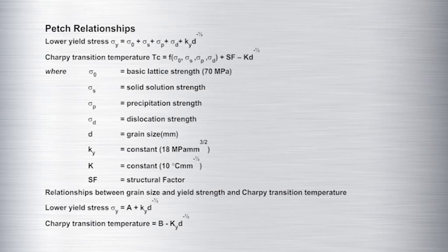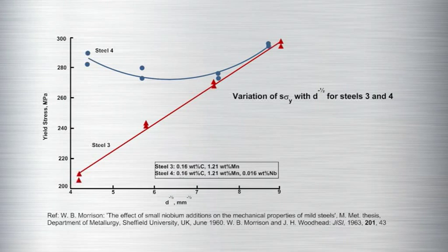It was found that the niobium effect was primarily due to a precipitation hardening effect. By heat treating the steel samples at different temperatures to try to plot linear Petch plots, we found that the niobium-treated steel did not obey the Petch relationship. At coarse grain sizes, there was a very large effect of niobium on the strength, but at fine grain sizes, there was literally no effect at all. We explained this by saying that niobium had gone into solution at the high temperatures required to form the coarse grain sizes and had reprecipitated as a very fine precipitate, giving precipitation hardening. At lower temperatures, where we were obtaining fine grain sizes, around 900 for example, the precipitation hardening was much reduced, grain size was refined, and fracture toughness was improved.